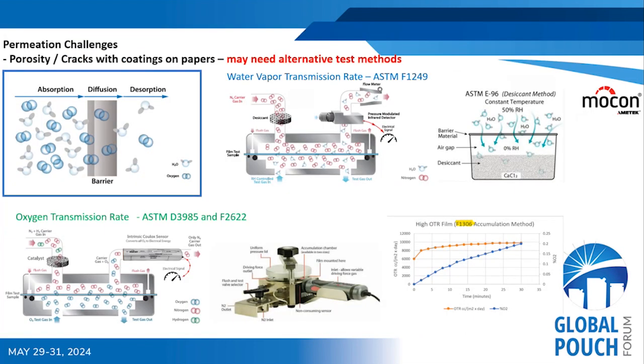On a similar note, there are also challenges to testing these materials. A typical permeation test is shown in the upper left-hand box. We have a process where there could be a test gas, could be oxygen, could be water vapor, could be CO2, depending on what gas of interest is needed for our package and the shelf life of the product. And you see a high cluster of gas on the left-hand side. Then that gas wants to absorb into the surface of the packaging material, and then wiggle its way or diffuse through, and come out on the other side.